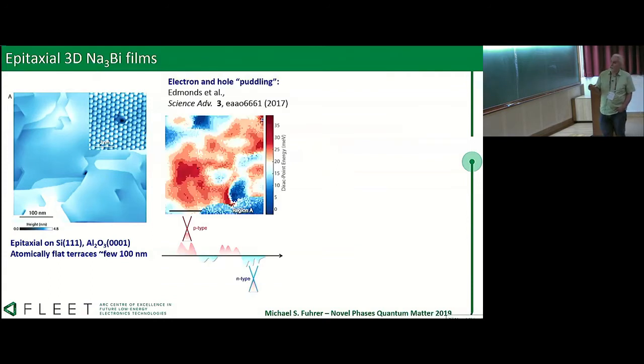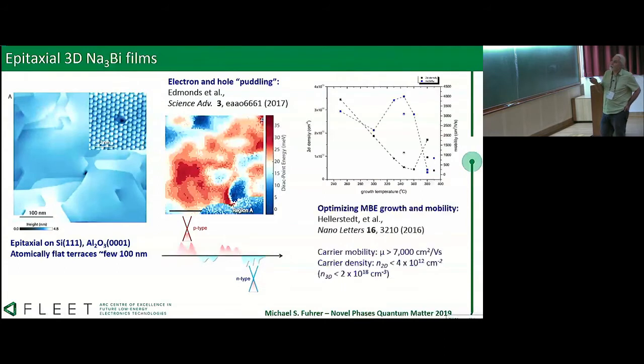We have looked at electron hole puddling, which is a ubiquitous phenomenon in Dirac materials. If you're familiar with graphene, it turns out that sodium-3 bismuth is quite smooth. It's as smooth as graphene on hexagonal boron nitride. The potential fluctuations are very small, and largely that's due to 3D screening. And we've been able to optimize the mobility. We can get mobilities of about 7,000 centimeters squared per volt second at low temperature, and carrier densities down to about 4 times 10 to the 12 in 2D, or 2 times 10 to the 18 in 3D. And so that's pretty good. This is comparable to the best really low-doped crystals. High-doped crystals may have higher mobility.